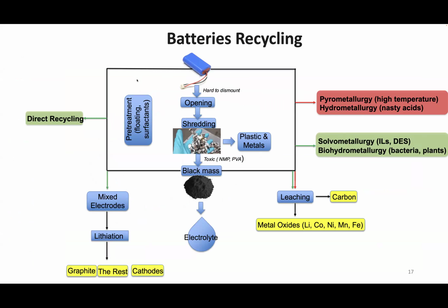There are significant research efforts, and significant companies are rising in this space, because we realize that actually our current batteries are reaching their first end of life, or maybe second end of life, and we really need to be better at giving a new life to these batteries. But the recycling of batteries today is still done a little bit like 18th century chemistry. You take the cells, you discharge them, you shred them into small pieces, you try to get out the plastic and metals, leaching metals out, and you get this black mass. Electrolyte is not really recovered. And so we still have some pretty old school methods, which are pyrometallurgy, where you burn everything at high temperature, or hydrometallurgy, where you use a mixture of really nasty acids to recover these metals.